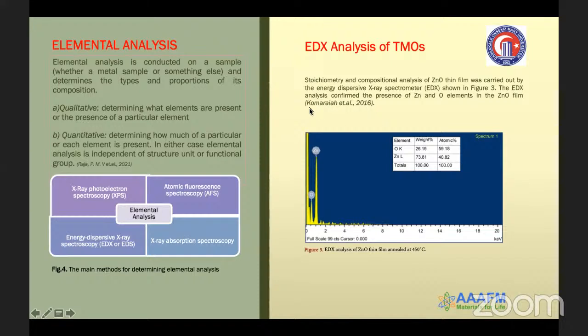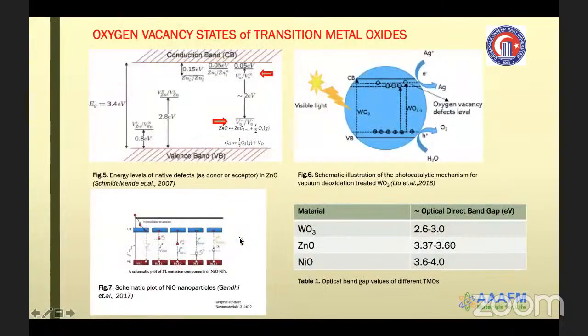In 2016, Komaraiah and colleagues presented a study. In this analysis, it is confirmed the presence of zinc and oxygen elements in this structure. So when we apply EDX on the material, although we know the elements in it proportionally, stoichiometric values may be low or erroneous due to excess of oxygen.